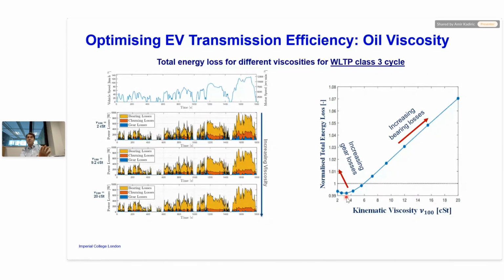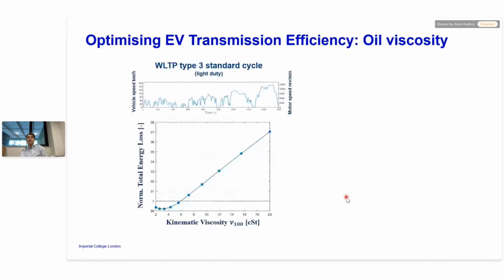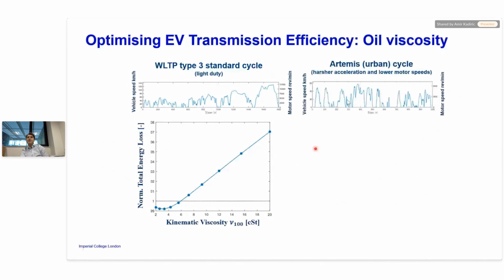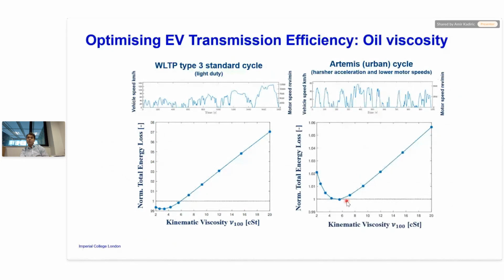If I change the vehicle duty, which is what we did next, so this is the same results on the previous slide, standardized WLTP cycle, which is the one that they use to publish their efficiency figures. We took another standard cycle called Artemis. Some of you might have seen this. It's an urban cycle where you have more rapid changes in vehicle speed, more acceleration, more deceleration, and so on. What happens then, if you do exact same calculations, the optimum viscosity is different. All of a sudden, it's closer to 5.5, 6 centistokes, 100 degrees.